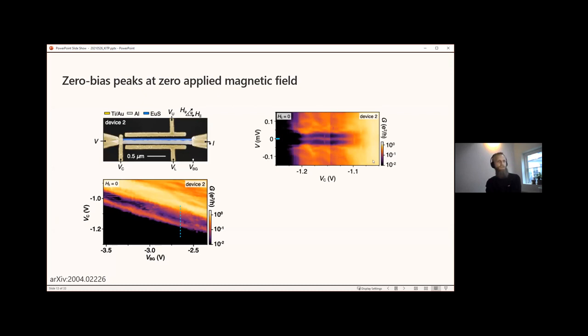cut off. And finally, in the tunneling regime, the spectrum represents the density of states at the end of the nanowire right here. And what we find, again, for this specific gate voltage, is that there is a zero energy state extending for a certain range of the cutter voltage, and an induced gap of roughly 50 microelectronvolts, which is strongly reduced compared to the bulk aluminum gap of 180 microelectronvolts.